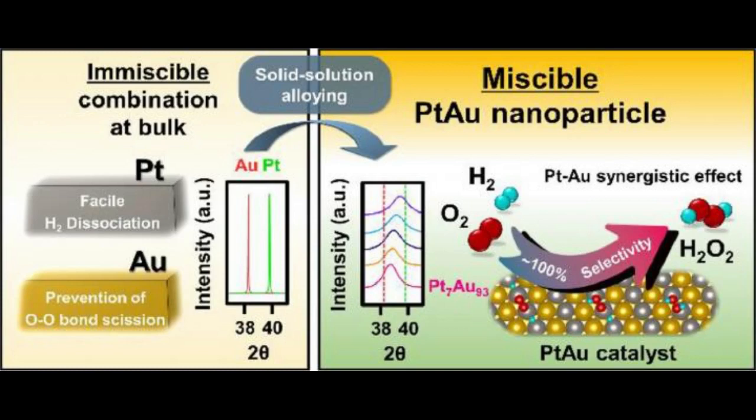In addition, a catalytic reaction can be maintained for longer than eight hours, resulting from the structural stability of the catalyst. The researchers also clearly established the crystal structure of platinum-gold alloy nanoparticles through additional computer simulations, which is difficult to solve using general material analysis techniques. Furthermore, the catalytic reaction mechanism was proposed at the atomic level, clarifying why catalytic performance for hydrogen peroxide production increases with increasing gold content.